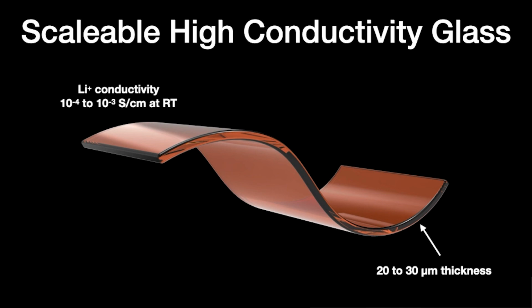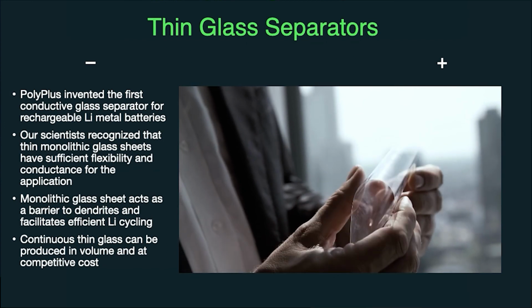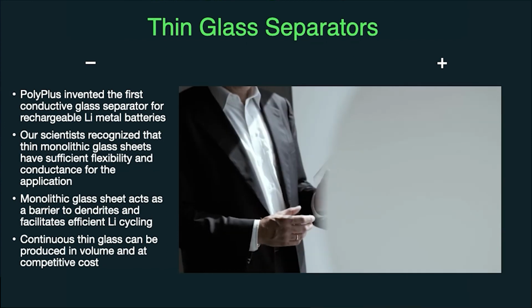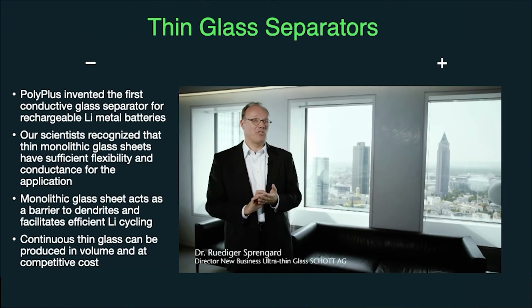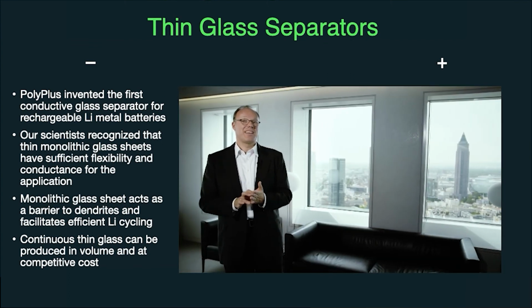So PolyPlus is working extensively in glass electrolytes, and the vision is to make these electrolytes not by sputter deposition, but by the same manufacturing processes that display materials are made, which is effectively melt processing, softening the glass, drawing, pulling, the way optical fibers are pulled. I'll show you a quick scenario of how that can be done. These are very conductive materials, approaching 10 to the minus 3 Siemens per centimeter at room temperature. Here you can see about a 50 micron sheet of glass. This is oxide glass, but being handled very much the way you would handle a polymeric material. They're very flexible when you get below about 100 microns thickness, and we take advantage of that flexibility with regard to manufacturing.